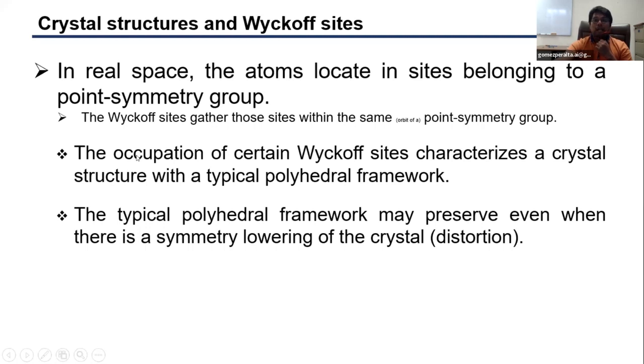And the occupation of these Wyckoff sites defines the typical polyhedral framework that characterizes a crystal structure. For example, in the perovskite structure, the characteristic polyhedral framework is octahedra. In blende or wurtzite, we can identify tetrahedra, and there are more examples in the literature. The typical polyhedral framework may be preserved even when there is a symmetry lowering of the crystal, as happens in perovskite compounds with a vertex-shared octahedral framework. The most popular picture of a perovskite structure is the one corresponding to the cubic symmetry, but there are perovskite compounds with orthorhombic symmetry, monoclinic symmetry, and even triclinic symmetry.